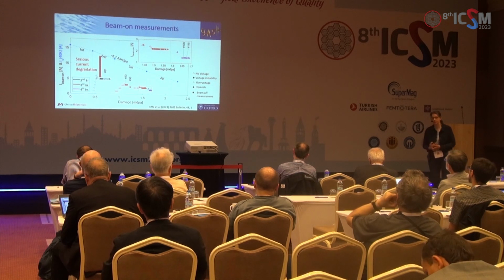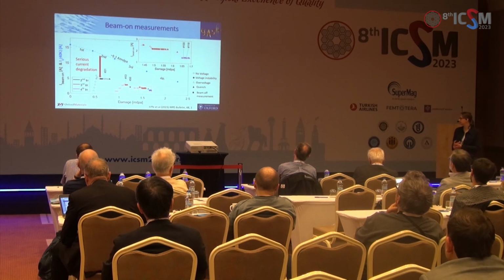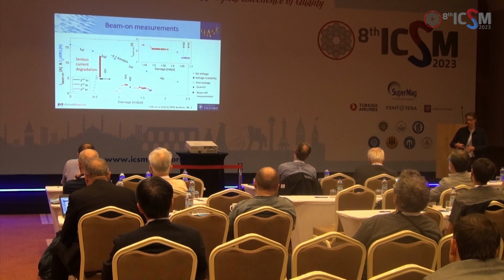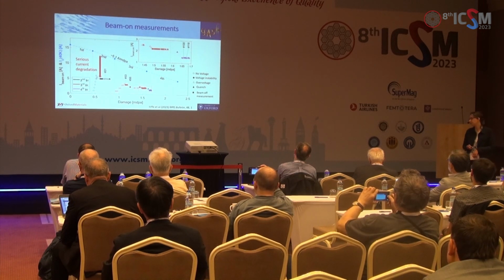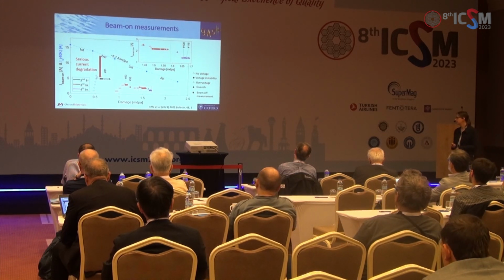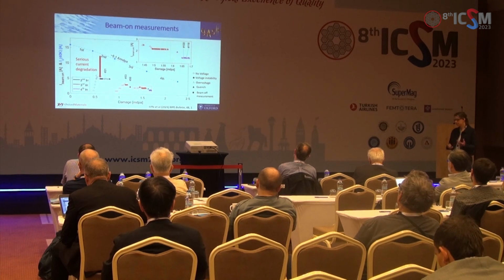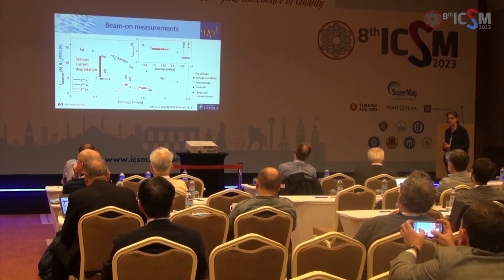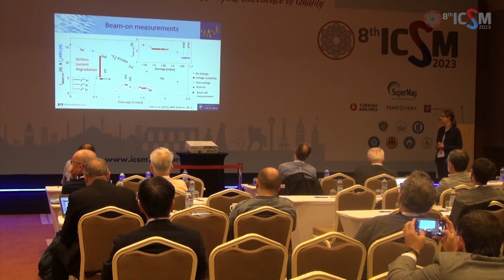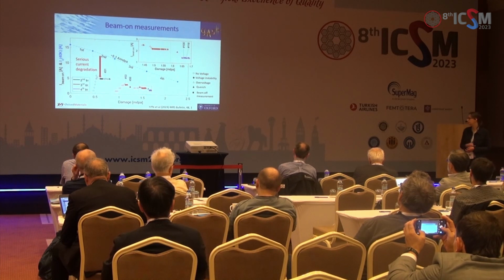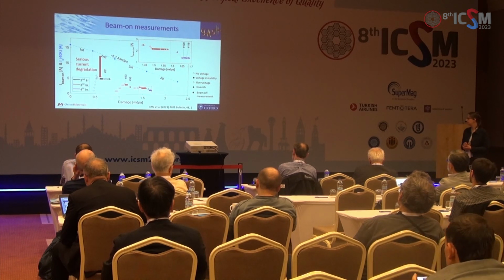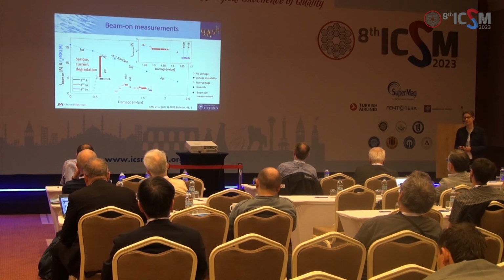We're trying to work out what the reason is for this. We've got some speculative reasons. We don't think it's just the whole sample heating up because of the energy of the ions being deposited. We think it is an effect of some sort of interaction with the electrons in the system, energizing those and then breaking Cooper pairs essentially to reduce superconductivity locally. But we're only speculating at the moment, so we need to do more of these experiments.